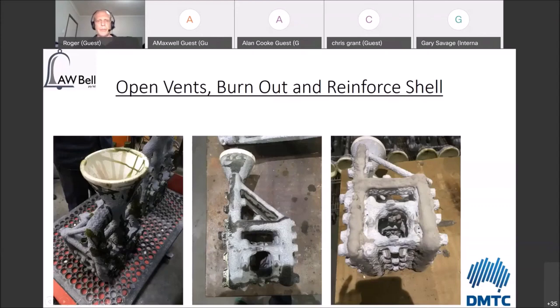Now, sometimes you reinforce the shell because some cracks may appear in the shell. Other times you do it just to give mechanical strength in the shell as well. And so here the vents are not being closed off, you can see these little thin vents, but the shell is being reinforced before doing that particular step. One of the reasons you have these is so that you can blow forced air down into these areas to get any ash or residue that might be in there and blow it out so that it can be removed.